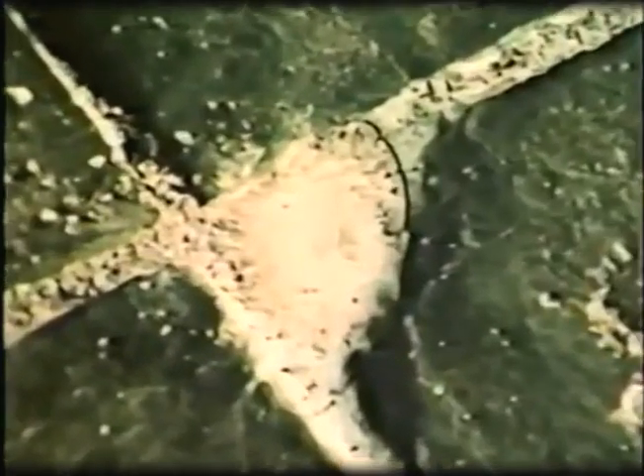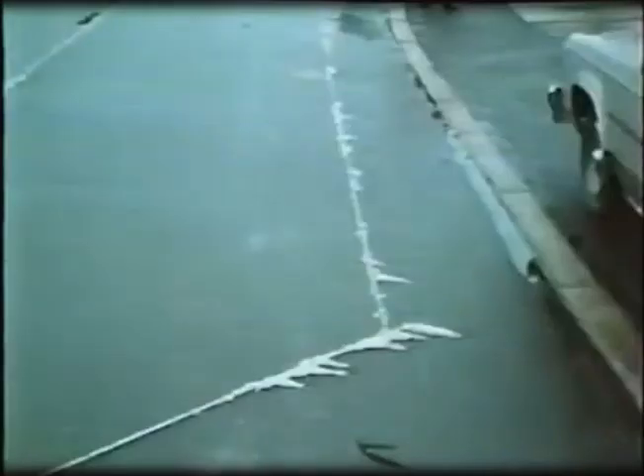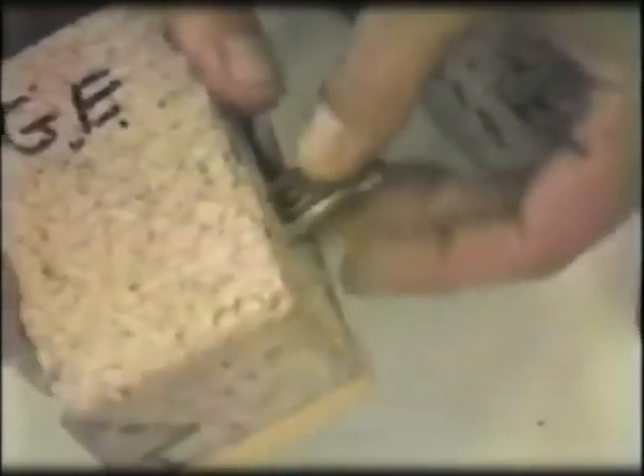Another major problem area is embedding sealant failure, which includes cracking, debonding, shrinking, tracking, and running out of the slot, or poor encapsulation of wire, all of which lead to loop failure. Bituminous-based materials, or hot tars, have been popular in the past because they were relatively inexpensive and easy to obtain. However, several problems exist with use of these materials.